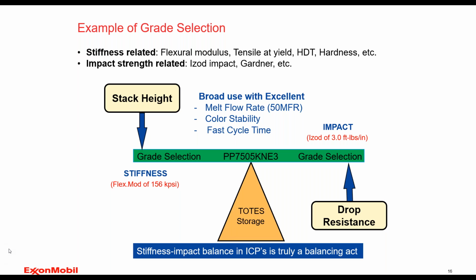When I get posed with a question like this, which grade is best, I recognize that totes are relatively large applications. They might have thinner walls, or certainly a producer of totes would be conscientious of that. And so I would start off by offering an ICP that's a 50 melt flow rate. The base componentry of that ICP would be to have good color stability, knowing that the parts are typically colored and have fast cycle times.